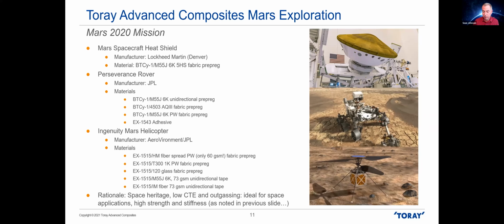T300 1K plain weave fabric, that's a very fine weave fabric that actually is fairly conformable and is good for things like doublers and hubs and the like there. The M55 tape is a very, very high modulus material. And it's made into a tape that's only 2.5 milli-inches thick. So you can ply those up very, very thin, I'm sorry, with a large number of plies to get balanced laminates and reduce your internal stresses in the laminates. So again, basically the rationale for these materials are space heritage, low CTE and outgassing, high micro crack resistance, and high strength and stiffness.